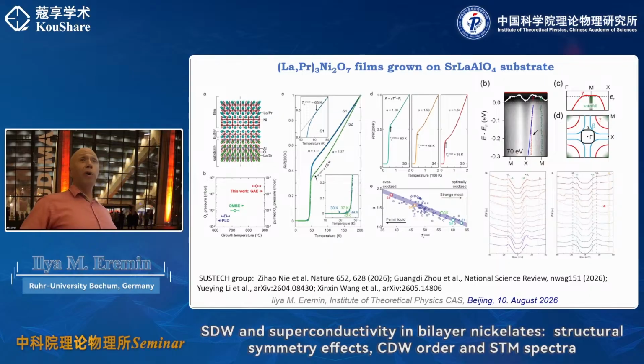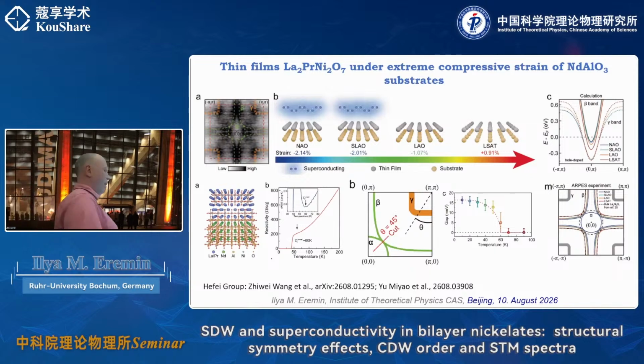Now, just before I came here to Beijing, there were another two papers that appeared just last week, coming from the Hefei group, which managed to grow superconducting films even under a stronger substrate strain, minus 2.14%. This is, as you see, a neodymium aluminum oxide (NdAlO3) substrate, which also shows onset superconductivity of about 60 K. One of the problems with thin films is that you need to show that superconductivity is really a thermodynamic feature and not filamentary.